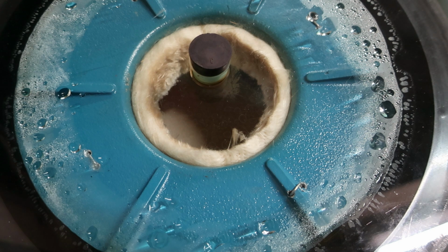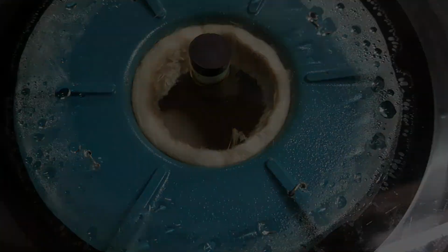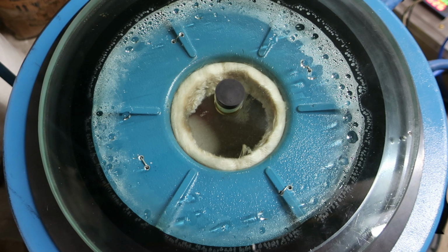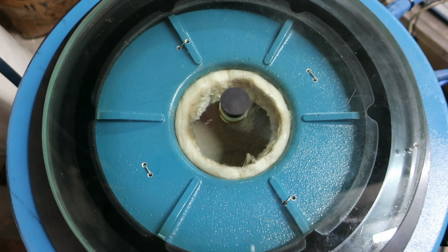It's a little longer and more of the condensation is gone. Most of the condensation is gone. The glass is hot to the touch. I'll give it a little longer. Basically, I think once all that condensation is gone, we're done. And here you can see, after 3 or 4 hours, the condensation is completely gone. Everything's up to temperature, and it's time to just let it slowly cool down.